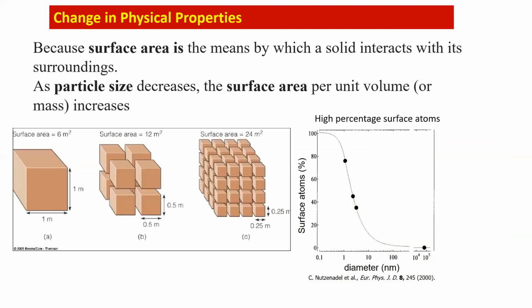So this is how the surface to volume ratio increases. In this figure, if you take the same size of material but divide it into smaller scale, the surface area of the material is around 6 meters square. But when the same material is divided into nanoscale and we reduce the scale, its surface area increases up to 24 meters square. So you can imagine how much it can increase when we go to the nanoscale.